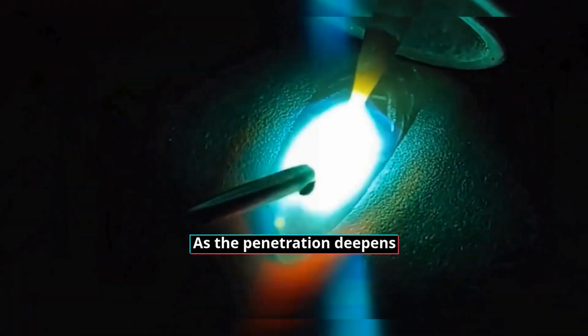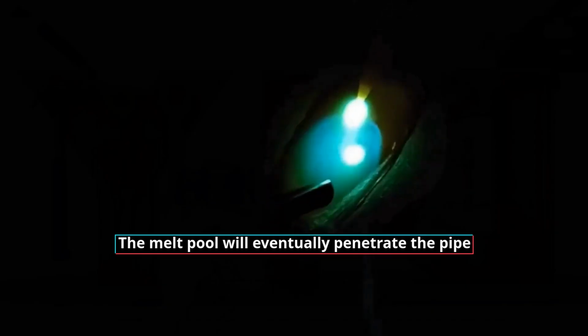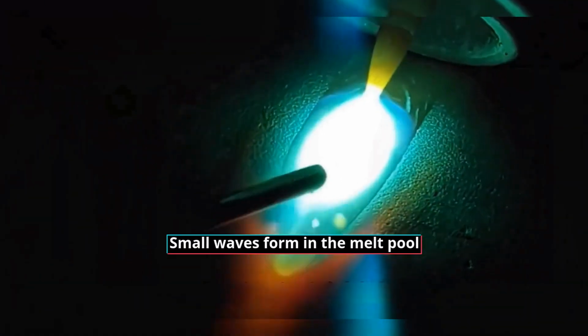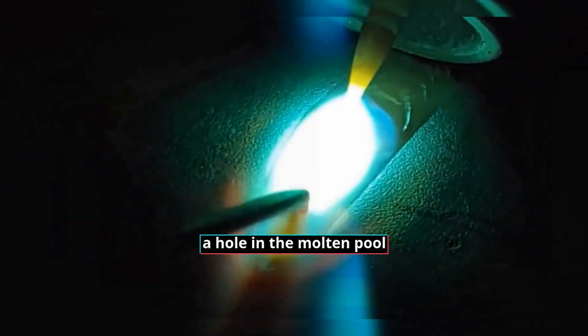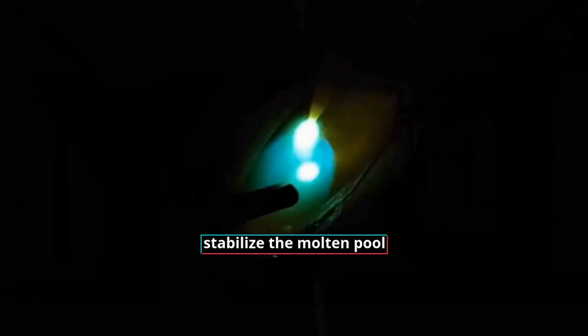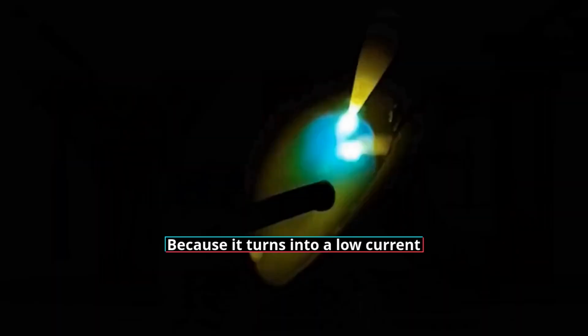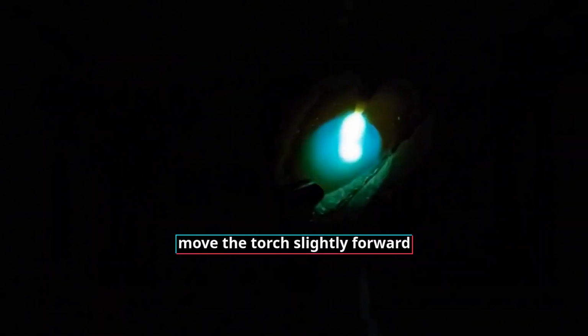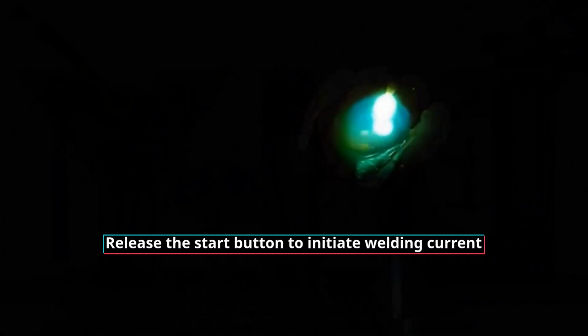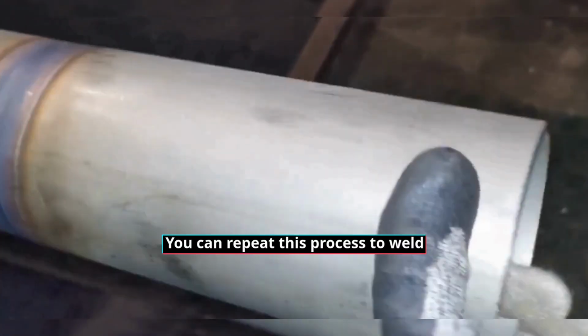First, weld it in place. As the penetration deepens, the melt pool will eventually penetrate the pipe. Small waves form in the melt pool. Then, provide a drop of filler rod. Press the start button before opening a hole in the molten pool. Then, stabilize the molten pool, because it turns into a low current. At this point, move the torch slightly forward. Release the start button to initiate welding current. You can feel the subtle waves again. You can repeat this process to weld.